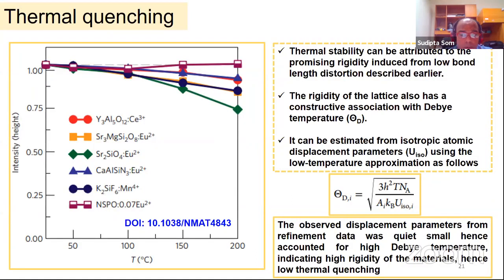So here I have shown some commercially available materials with different thermal stability, and another parameter associated with this thermal stability is the Debye temperature. We can calculate this Debye temperature in two ways. One is DFT simulation, another we can calculate from the isotropic parameter we have got from the Rietveld refinement. If we get a high Debye temperature, that indicates high rigidity of the material, and high rigidity indicates low thermal quenching. In our case, we are getting a very high Debye temperature compared to the commercial one, and this indicates a low thermal quenching material.